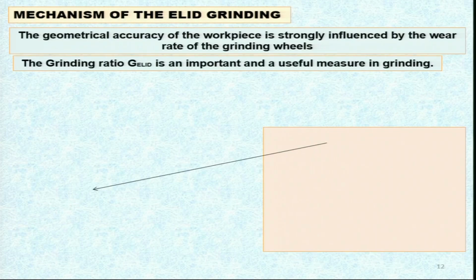The grinding ratio G ELID is an important and useful measure in grinding. You can see here G ELID is given by the volume of oxidized material on the wheel, the volume of oxidized layer removed during the grinding process, and the volume of material removed from the workpiece. So, whatever is being removed from this grinding wheel divided by the workpiece, that will give you the G ELID.